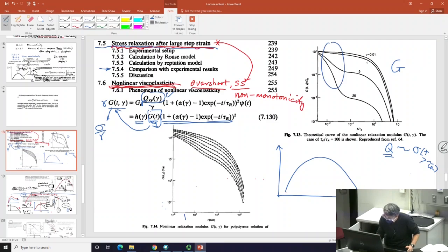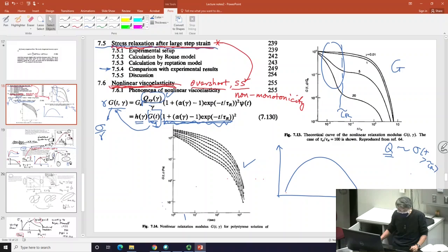It shows the kink. This kink is due to this parameter, showing the loss of stress due to chain retraction, Rouse chain retraction, occurring at the time scale of Rouse time. And this is the data. The rest is history, that one could try to make some quantitative comparison, at least for a subset of data. Okay? So this is just a little more of a supplement to what I said last time.